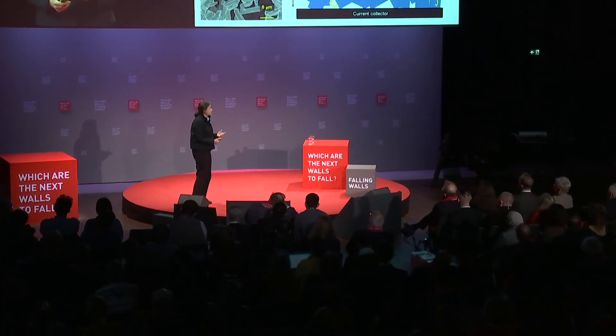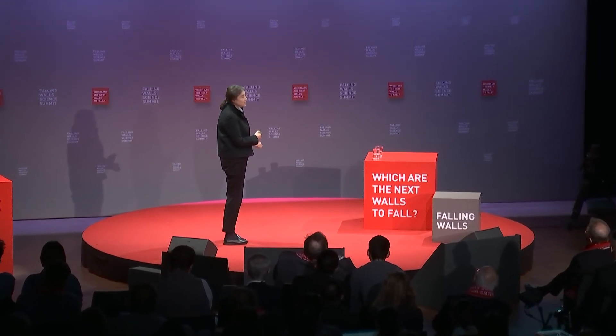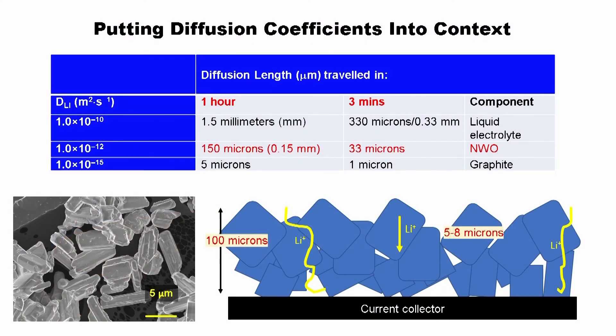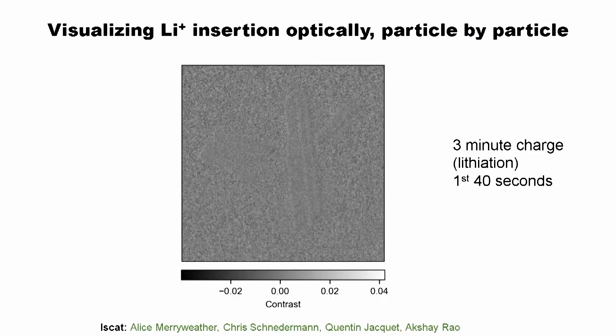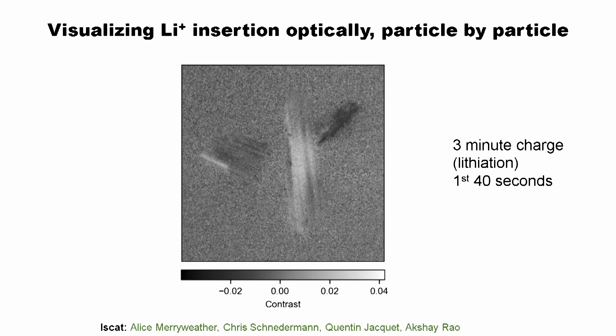There's a lot of discussion about nano-sizing and it's assumed to be good, but in practice a nano material has a very high surface area and can react with the electrolyte, causing battery degradation. So we can use large materials and achieve a three-minute charge. Graphite — the commercial material — in the equivalent time, lithium ions have only moved one thirty-third of the distance.